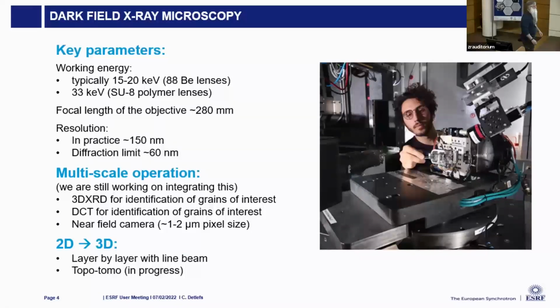So key parameters: typically we work at X-ray energies between 15 and 20 keV. We can go up to approximately 30 keV. And we have a working distance between the sample and the X-ray optics of about 20, 30 centimeters. And that leaves a lot of space for sample environments. For example, for metallurgy, we've had load frames to actually pull and plastically deform the sample during the experiment. We have furnaces, we have cryogenic environments and things like that.